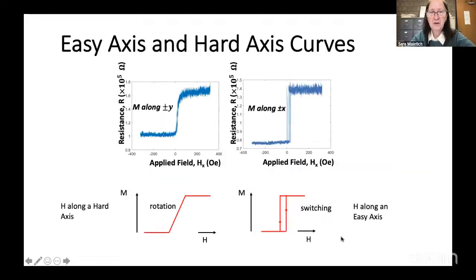And just to review, for people who aren't in the magnetics area, if you've got a field along an easy axis, which can be defined by the shape for these elongated nanomagnets in traditional spin ice, or here by the magnetocrystalline anisotropy, which is very low for cobalt iron boron, you would get a switch up and a switch down. This is just happening very, very quickly. So we see the telegraphing. We see telegraphing at or near zero field, which is good for low energy.